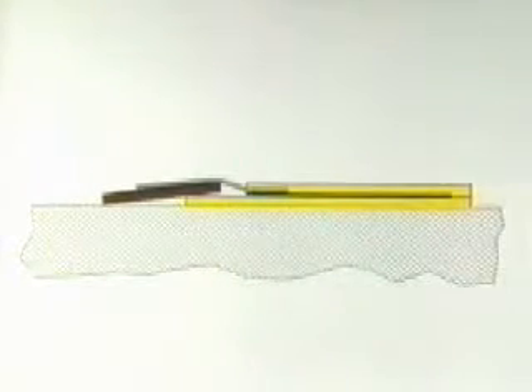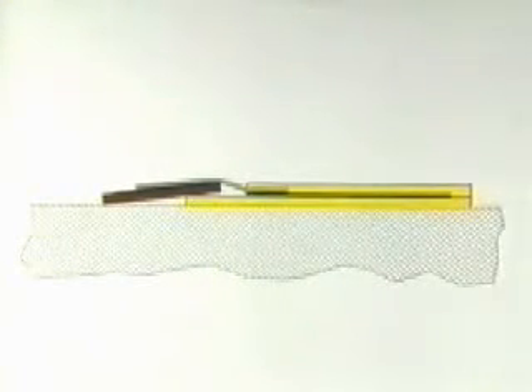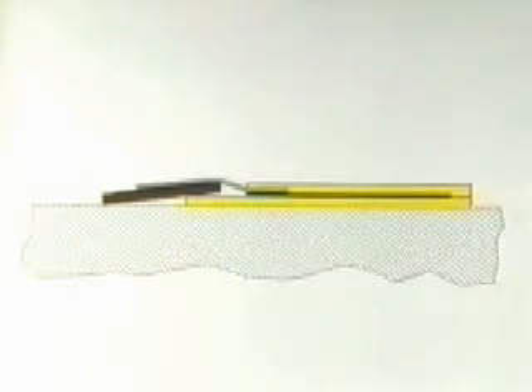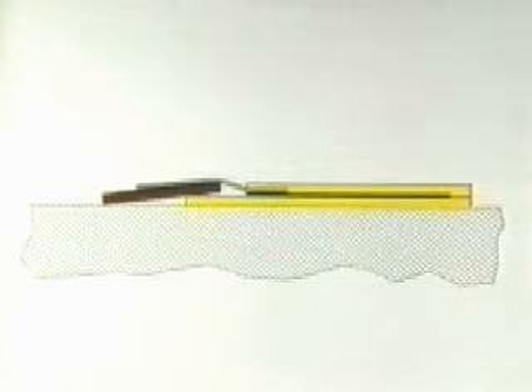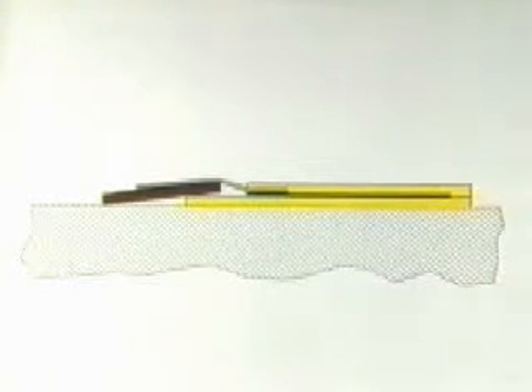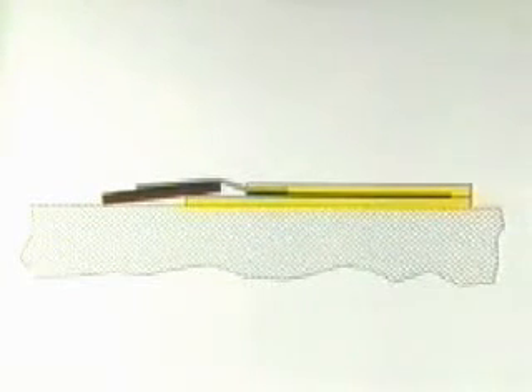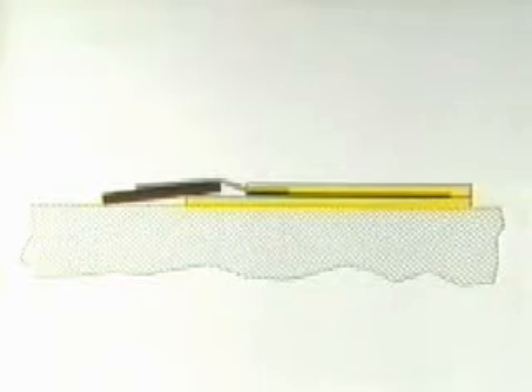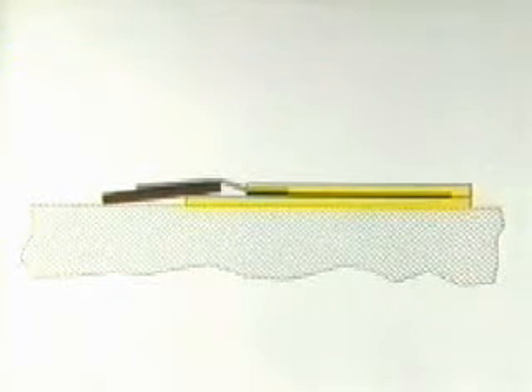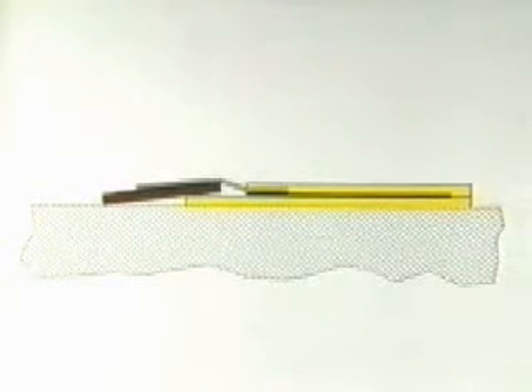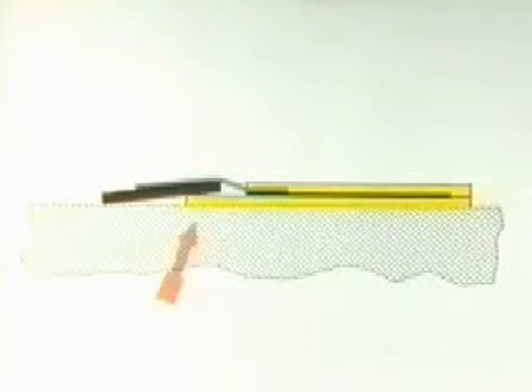Here you can see the free edges of the strain gauge. The solder terminal that has been previously prepared is joined to the strain gauge so that both can be mounted in one working stage. The solder terminal must be pushed between the base film of the strain gauge and its connecting strips, so that the insulating films overlap to prevent a ground connection.